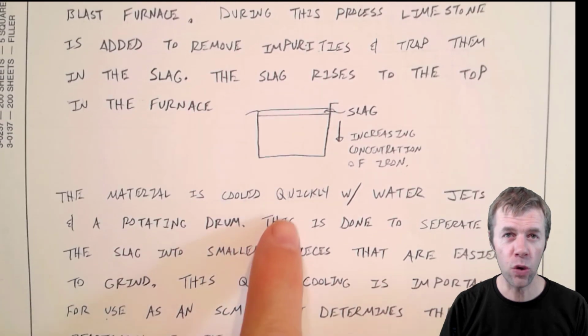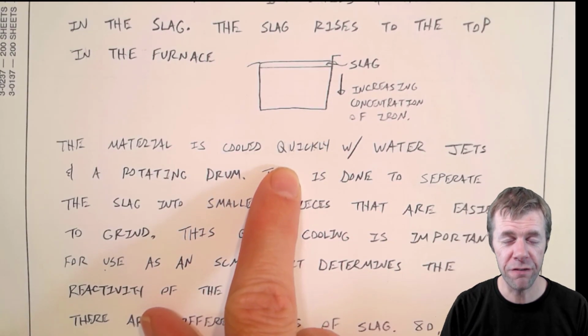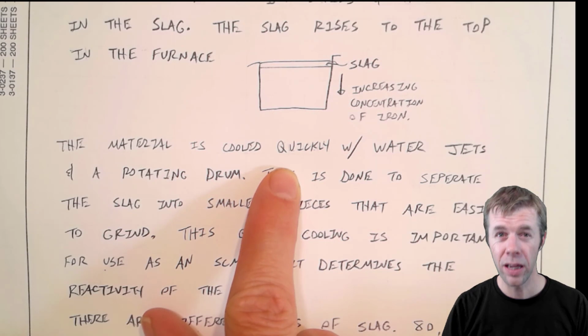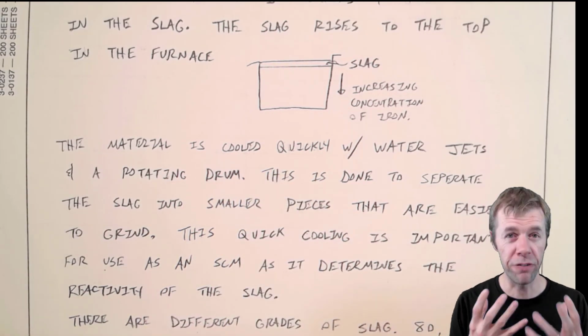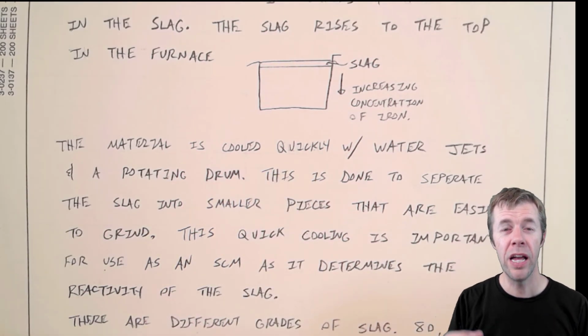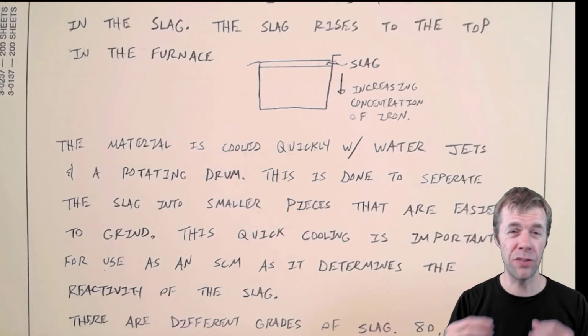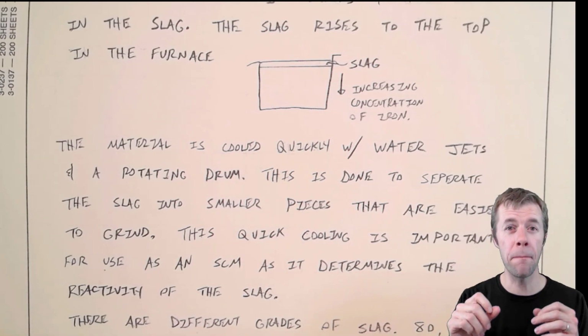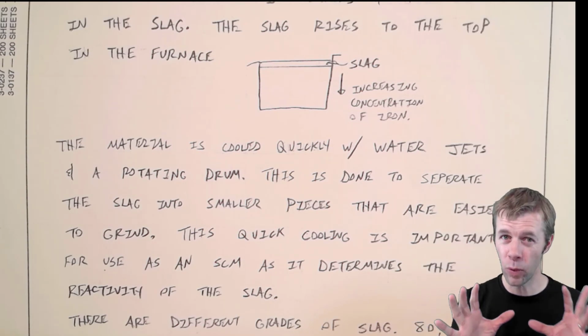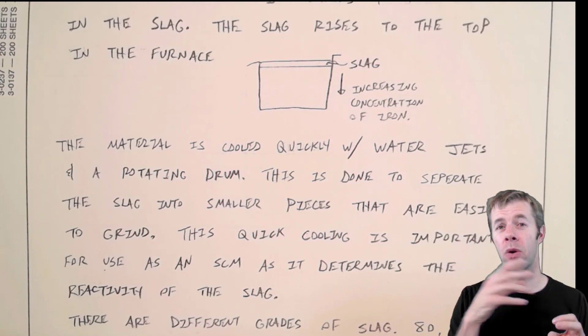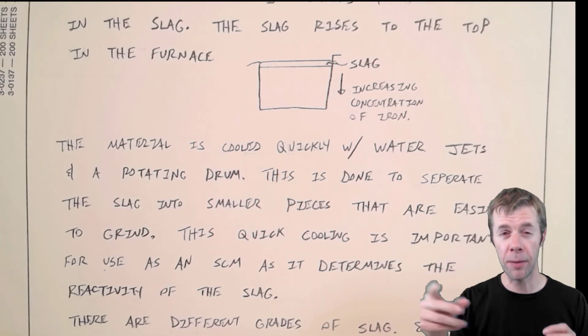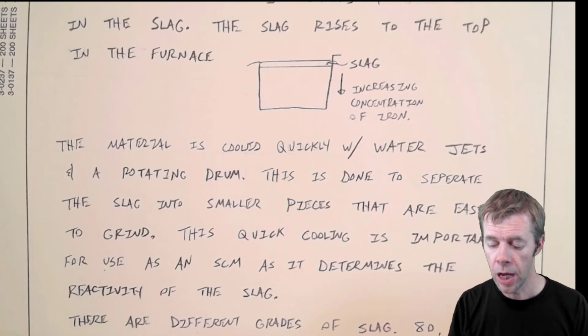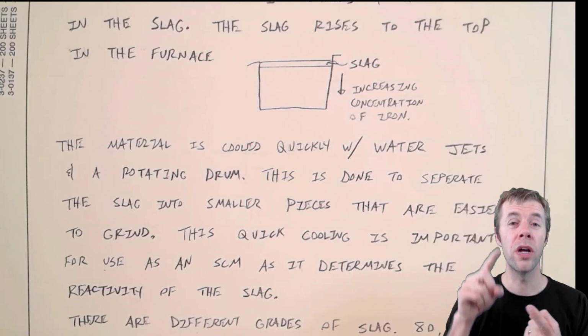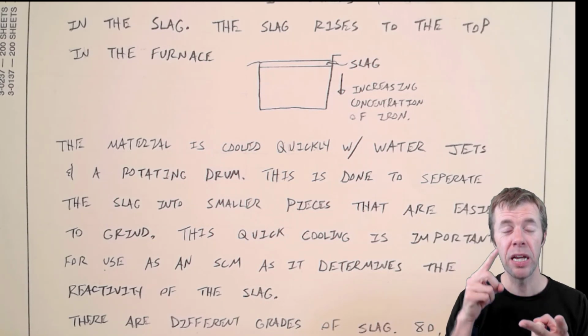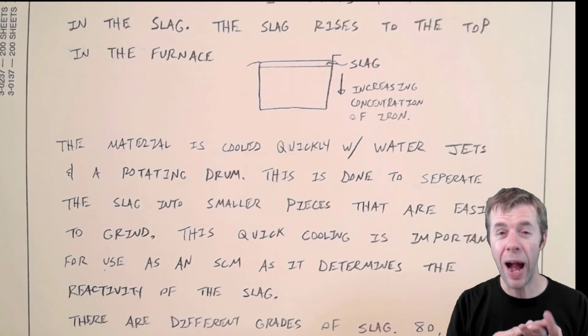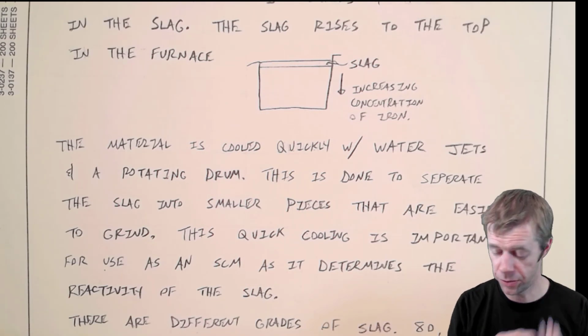You have to quench it. You have to cool it very, very quickly. Why? Because you want to make it glassy. You want to make it amorphous. So you want to get the material off, and you want to cool it with water jets, and then sometimes they'll have a rotating drum where they break it up. There are lots of different ways to produce slag, okay? And they are always refining that process to make it better. But the key is you want to get it cool quickly, and you want to break it up into small pieces so it can be ground into even smaller pieces.